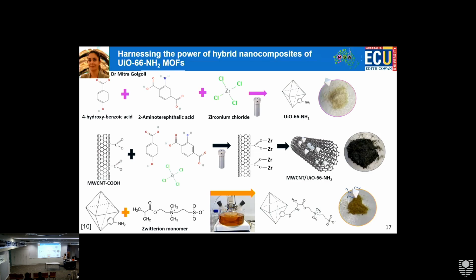With that, this NH2 is the same functional group as one of the monomers, so it can chemically bond during the membrane formation process. So basically in here, Mitra has done double modification. She has done multi-walled carbon nanotubes in addition to UiO66. In this case, she did in situ formation, so adding multi-walled carbon nanotubes into the autoclave together with the precursors of this MOF, and then creating this composite structure.